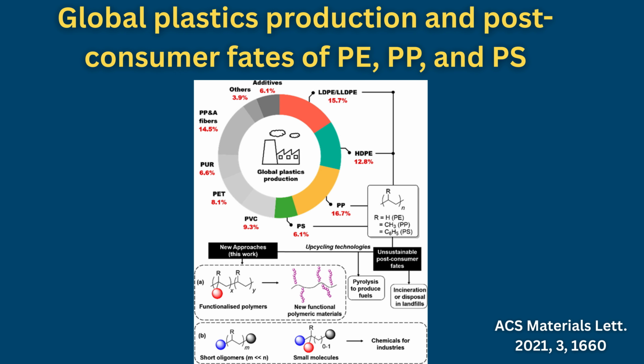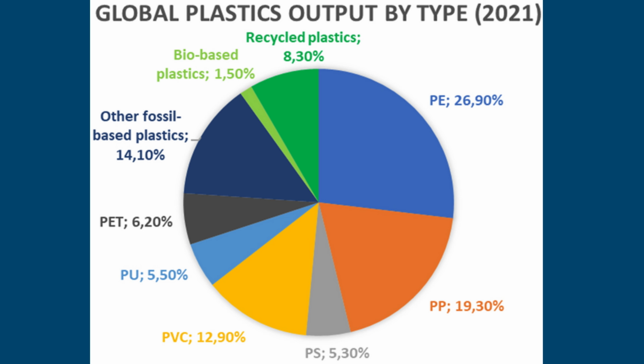Polyolefins, scale and waste challenge. The dominant commodity polyolefins, polyethylene, PE, polypropylene, PP, polyvinyl chloride, PVC, and polystyrene, PS, are derived from simple alkenes, ethylene, propylene, vinyl chloride, and styrene. In 2021, PE accounted for approximately 27% of global plastic production, PP for approximately 20%, PVC for approximately 13%, PS for approximately 5%. Together, these materials represent roughly two-thirds of total plastic production and waste. Their low cost and widespread short-term use have intensified disposal challenges.